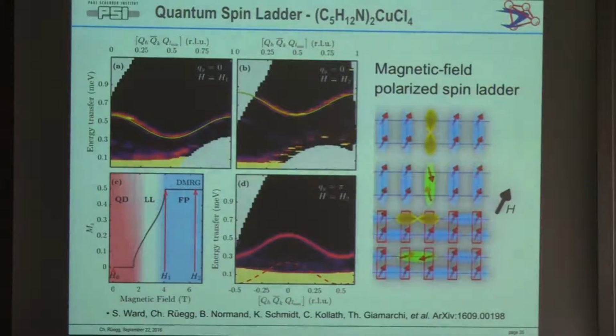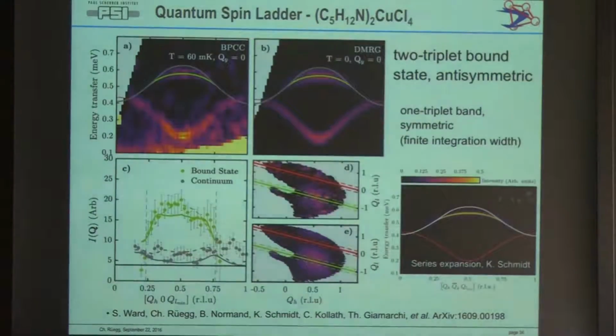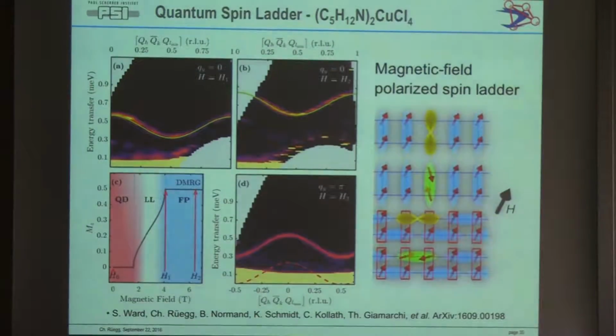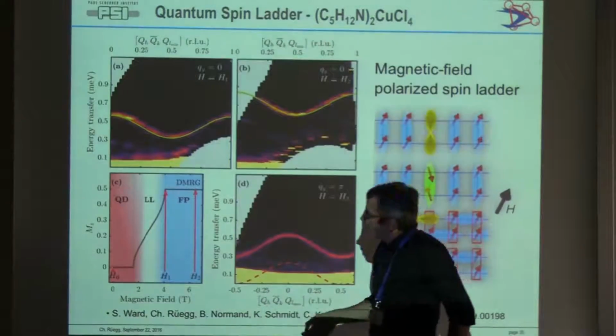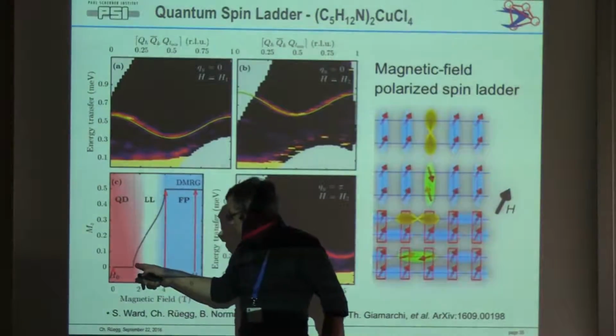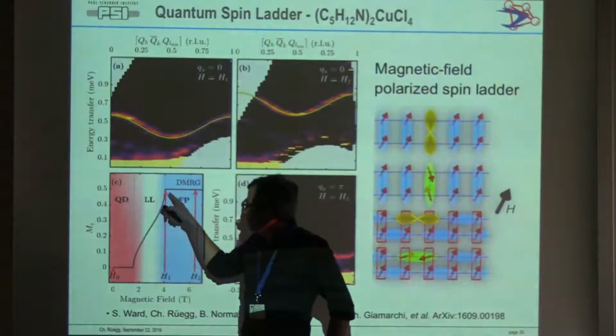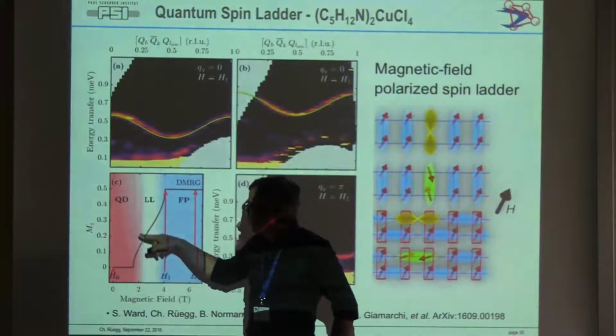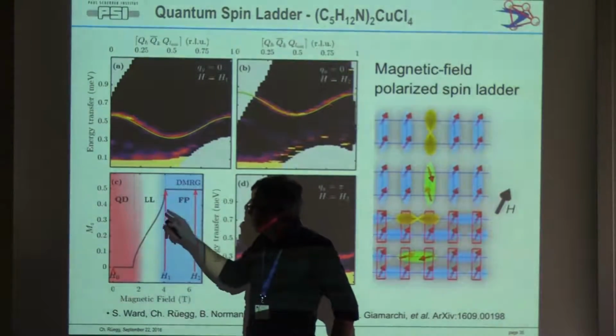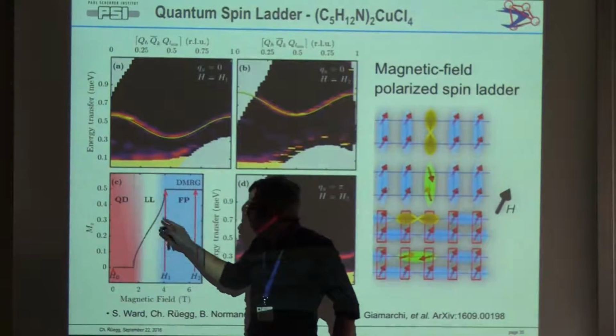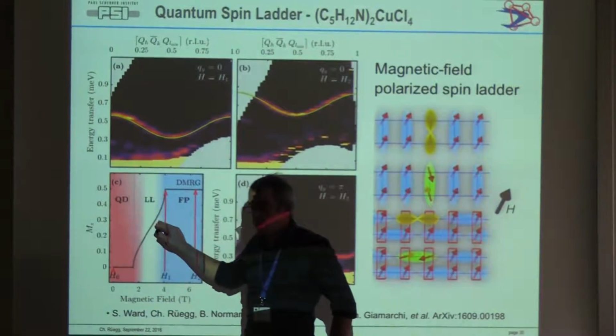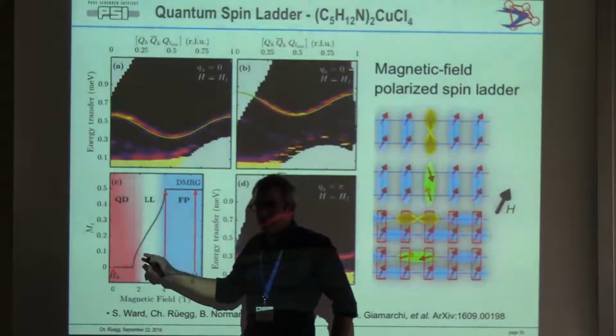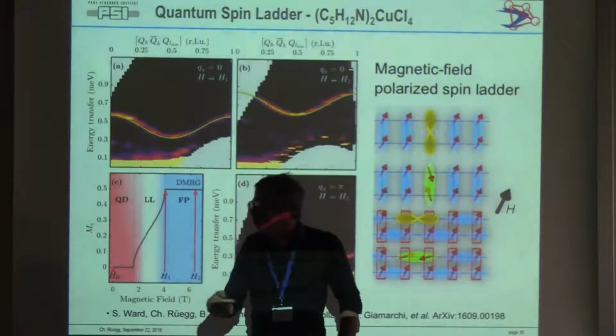So now about high magnetic fields. Why is it so interesting now to play around, and to first show you some data? When you now apply a magnetic field, the magnetization curve would somehow look like this. You close the gap which we just measured, you get the finite magnetization, and this regime in the middle will be a Luttinger liquid. And we come back to this later. The excitations we measured as well, but I cannot discuss in all details. You see a spinon spectrum at half magnetization. It looks exactly like a spin-1/2 chain we have seen in your talk.